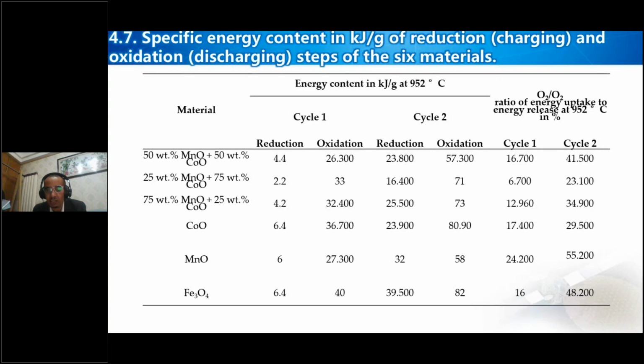We also measured the energy content, energy density at 950 degrees centigrade. We get different results in cycle 1 and cycle 2. So the main focus out of the others is still the 50% composition of manganese oxide and cobalt oxide. So in the first it is 16.7, the second is 41. So when compared to the others, except manganese oxide 24.2 and then 55.2, occasionally it happens. Otherwise, still the other compositions, the 50-50% is on a good track.